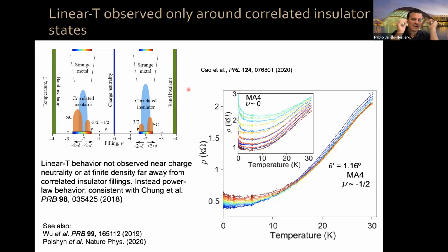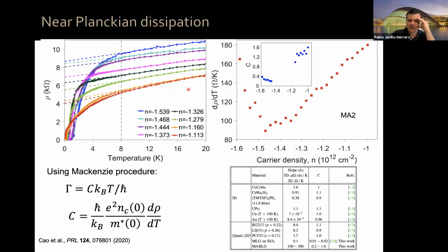Now, for some devices which are very clean, we can actually measure the scattering rate. This coefficient happens to be h bar over kB, and then other fundamental constants, and then the charge density, the effective mass, and the slope, d rho dT. So we can measure all three quantities, in particular the effective mass through the temperature dependence of the Shubnikov-de Haas oscillations. So we can measure this coefficient as a function of doping, again, because we can continuously change our doping.